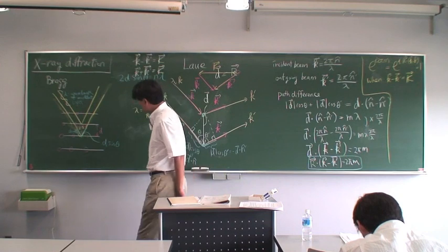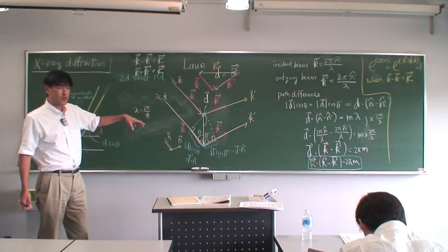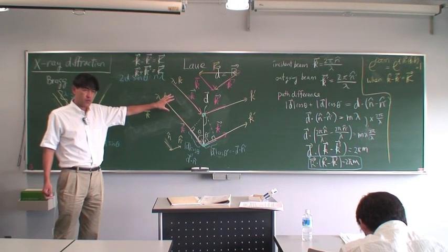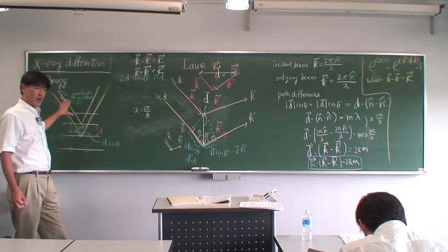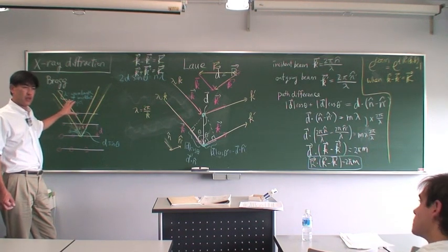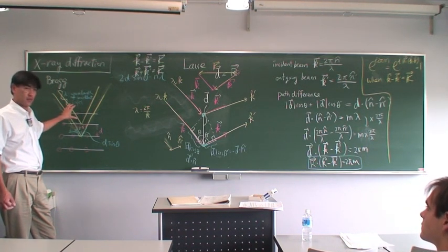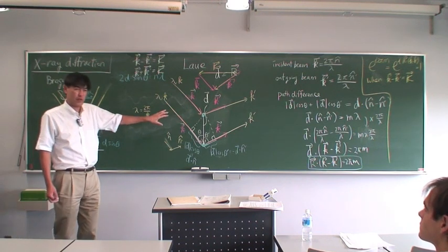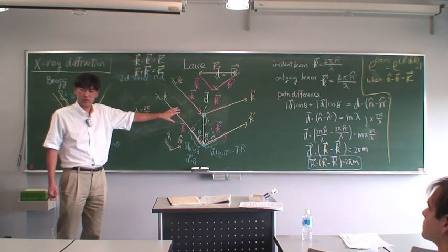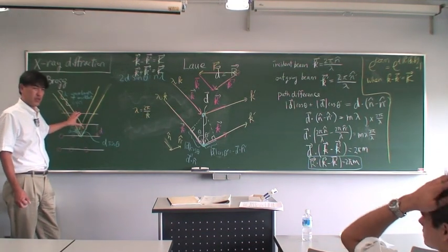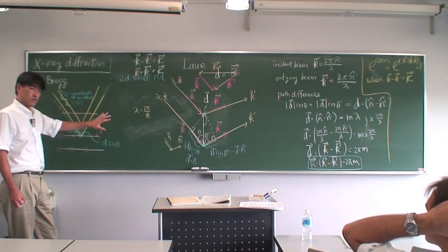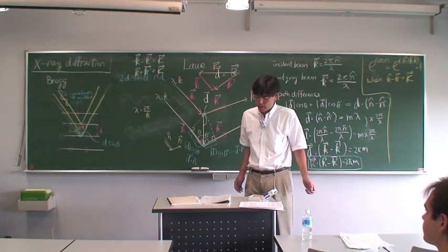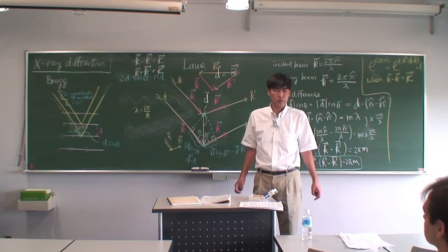It is also easy to show that Laue's formula and Bragg's law are practically equivalent. This is why the empirical formula is always used: you can always think about the reciprocal lattice, but sometimes it's too complicated, so you just look at the lattice plane. It is written in every textbook.